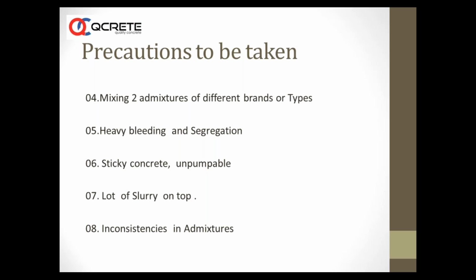So if we don't do a trial and don't fix a proper dosage of both the regular superplasticizer we are using in conjunction with what is supposed to be used as a waterproofing agent, we are going to end up in set retardation or air entrainment or strength loss or something like that. We also sometimes see heavy bleeding and segregation.